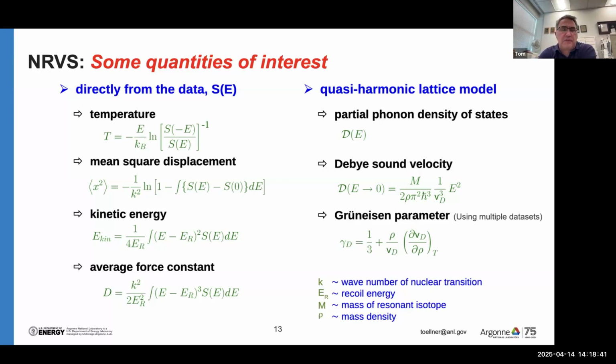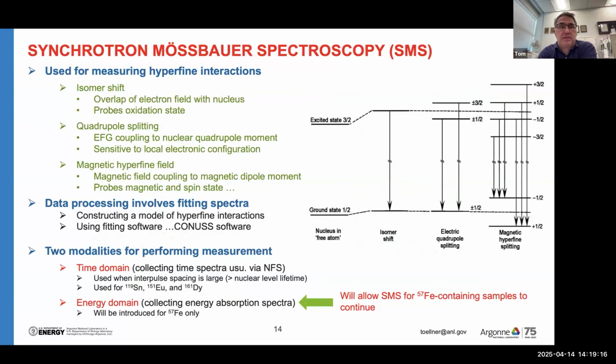Actually, it's the second derivative of the interatomic potential along the beam direction, but you can assume it's a constant at a fixed temperature. If you assume a quasi-harmonic lattice model, you can extract the density of states and all the quantities that come from that, of which there's quite a few. And then there's the Debye sound velocity, as I mentioned. You can also get the Gruneisen parameter if you take multiple data sets and vary the volume or the density, of course, and then you can extract a Gruneisen parameter.